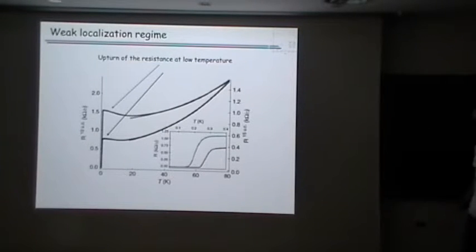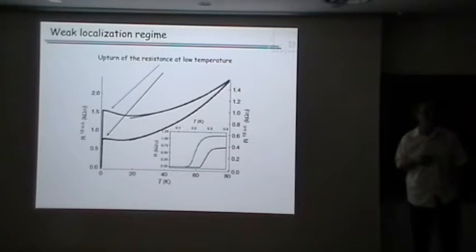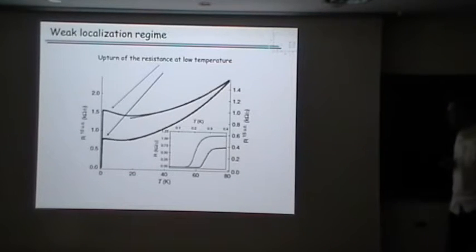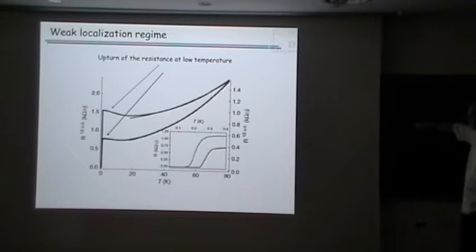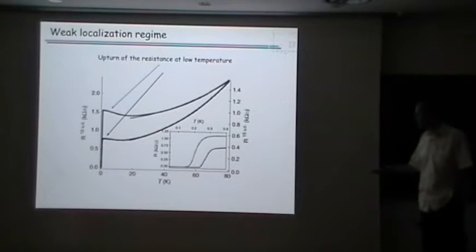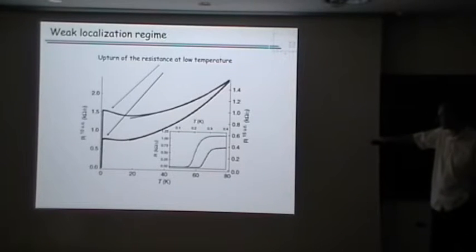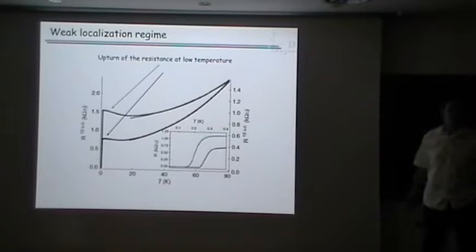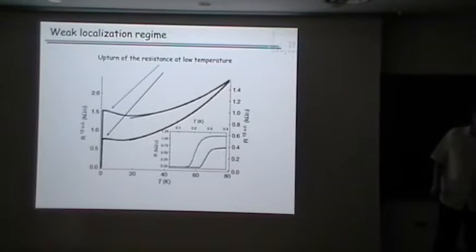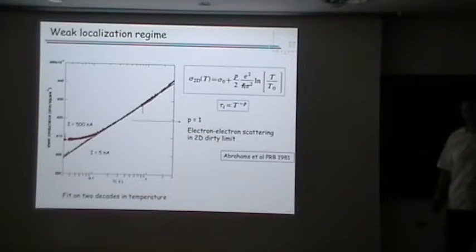And the last part of my talk is about transport and magnetoresistance in those systems. Again, we don't have any sign of hysteresis and stuff like that in our measurement. I mean, there is no sign of magnetism whatsoever. But in fact, at low temperature we always have weak localization before the superconducting transition, in the region of 10 Kelvin. Of course, since it's a 2D system, you think about weak localization effects.